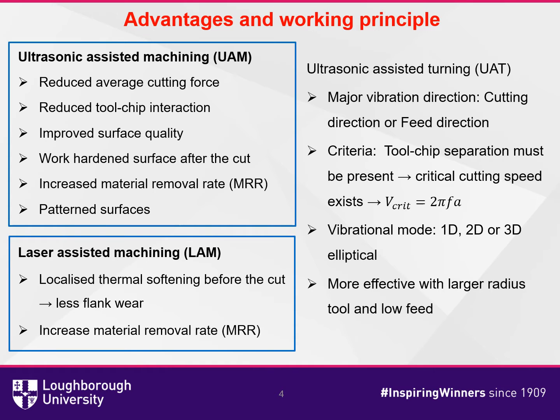Vibrational mode can be 1D, 2D or 3D elliptical depending on your transducer design. In most cases, perfect 1D motion of vibration is difficult due to mass sensitivity of the total design. To achieve the best surface quality for 3D elliptical with major vibration in the cutting direction, large tool radius and low feed is required for a polishing effect to be maximized.